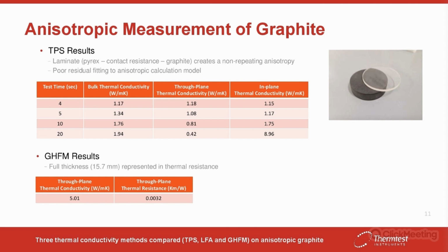And then as you penetrate past the Pyrex, that structure is no longer repeating and well organized. So it's really not unexpected that these results would not be truly representative of the sample through the whole thickness. But it's an interesting phenomenon to see. Basically, you see some sensitivity due to the heterogeneous nature of it. Again, if you were to use any one of these timescale results, whether it be average or anisotropic, given that it changes throughout its thickness, the rule of thumb would be to measure as much of that thickness as possible.